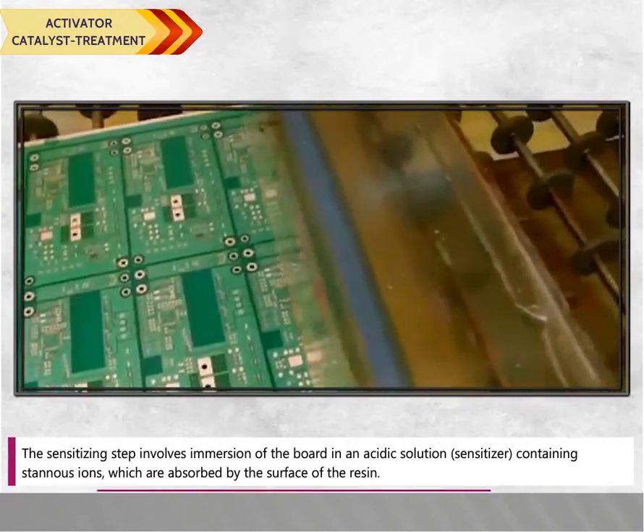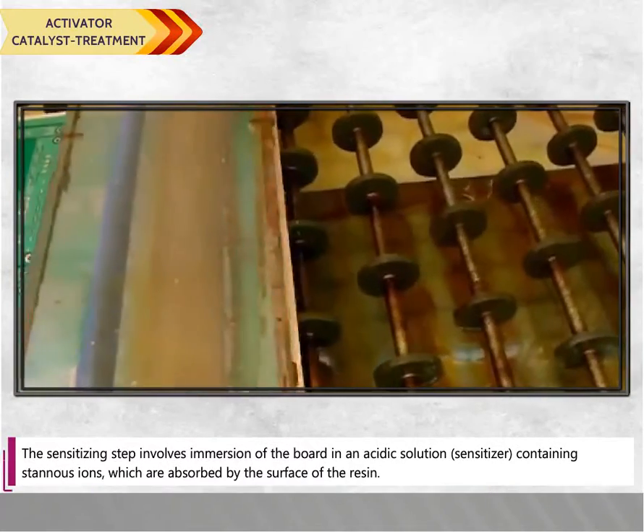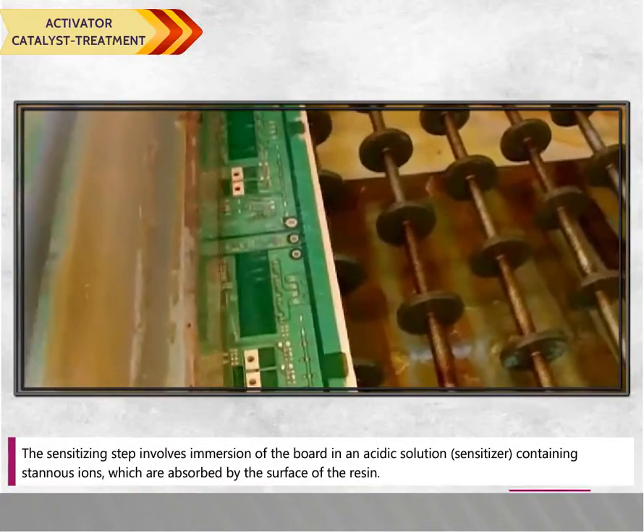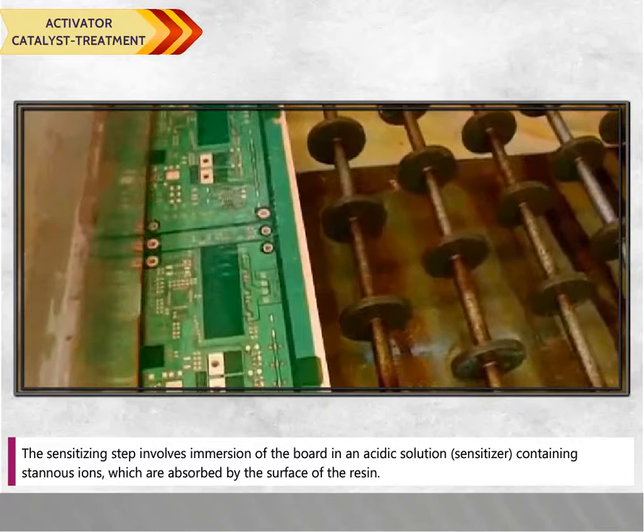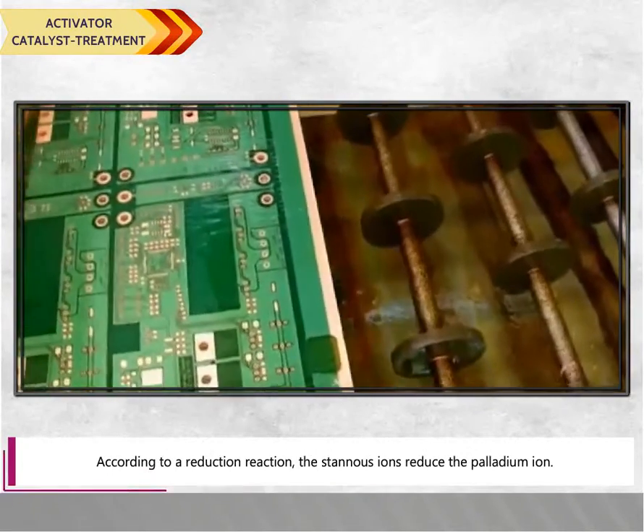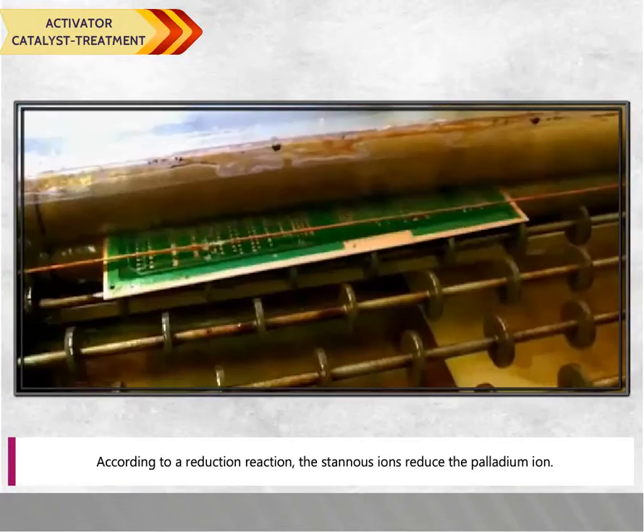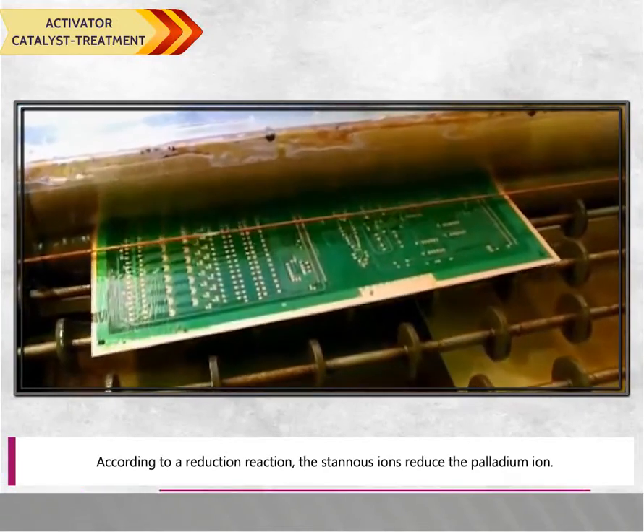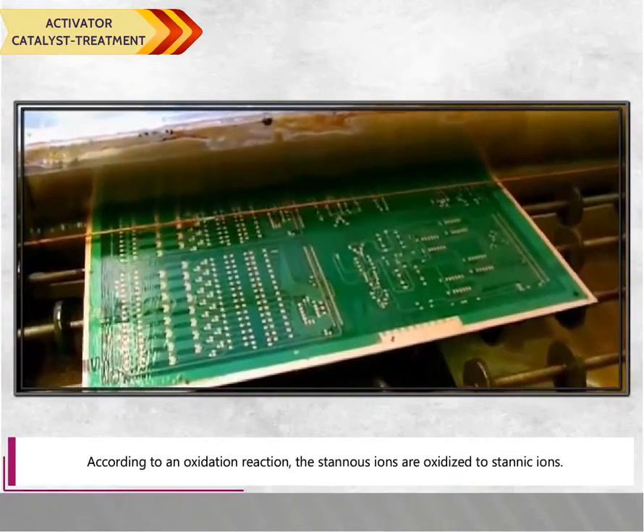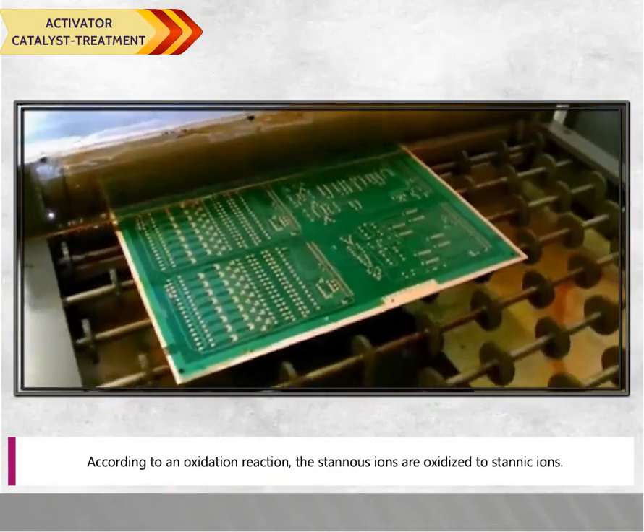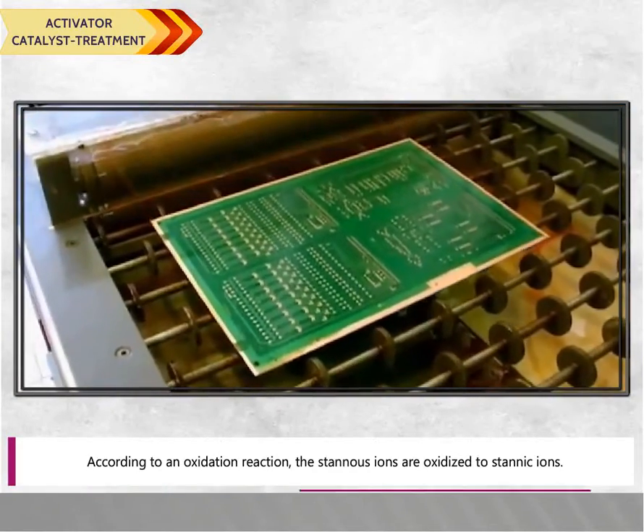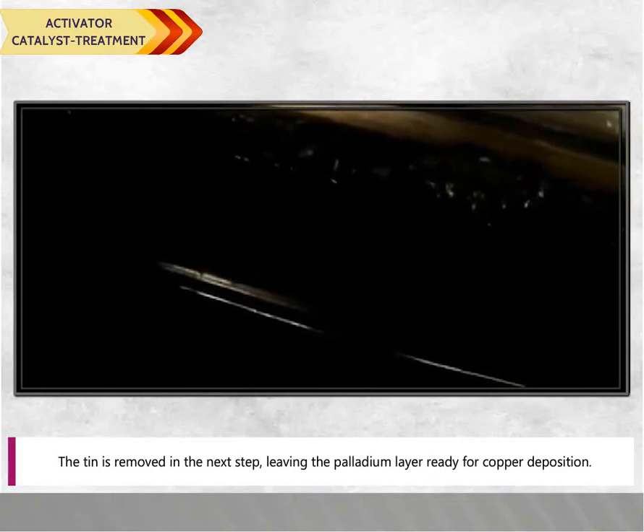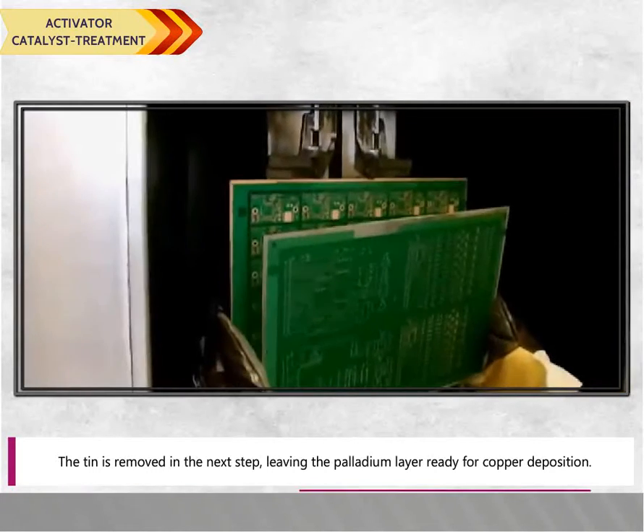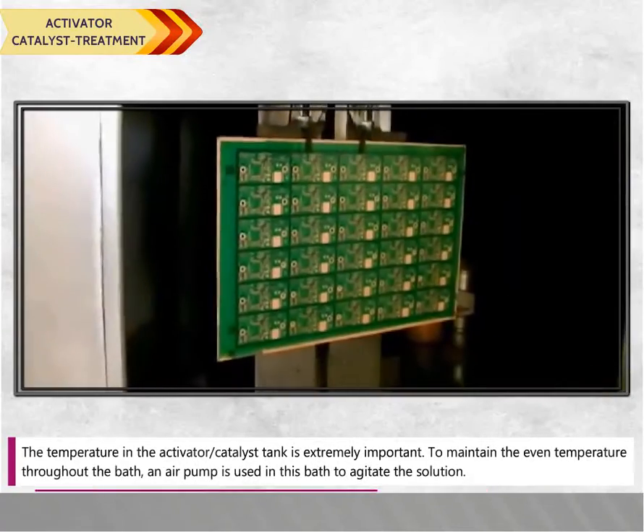The sensitizing step involves immersion of the board in an acidic solution, that is the sensitizer, containing stannous ions which are absorbed by the surface of the resin. According to a reduction reaction, the stannous ions reduce the palladium ion. According to an oxidation reaction, the stannous ions are oxidized to stannic ions. The tin is removed in the next step, leaving the palladium layer ready for copper deposition.